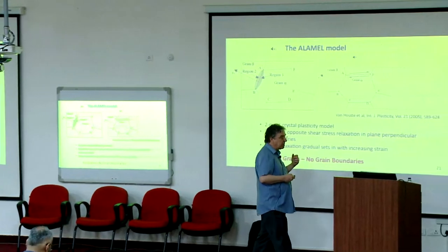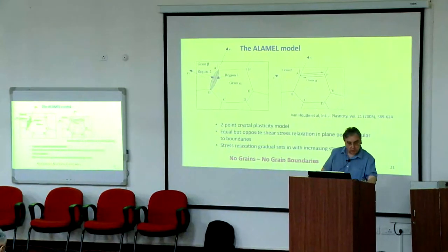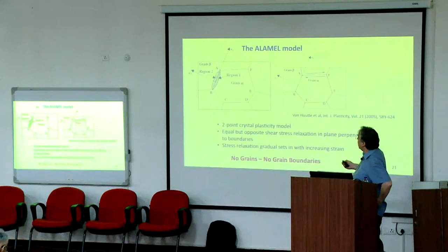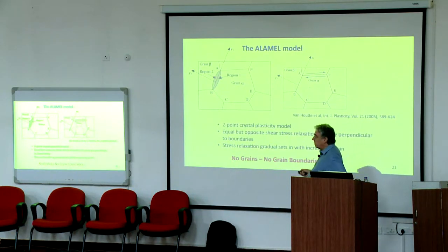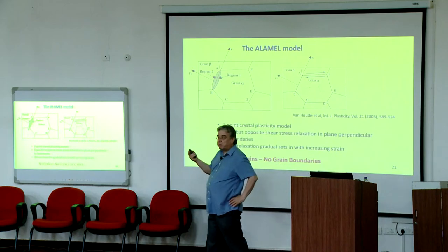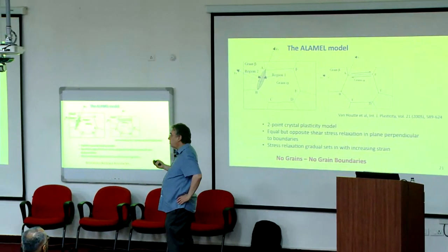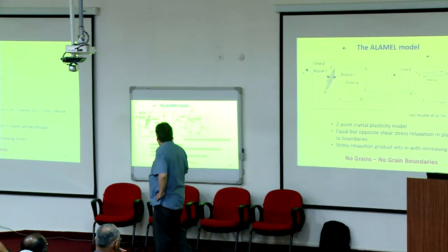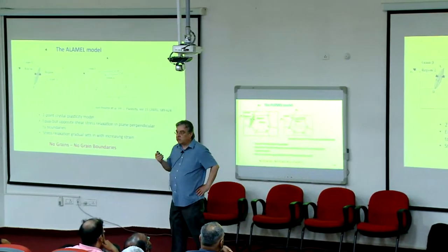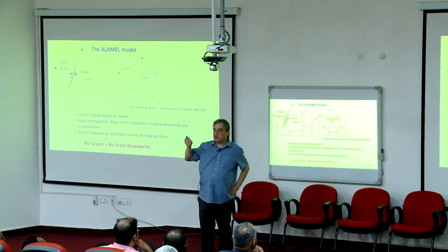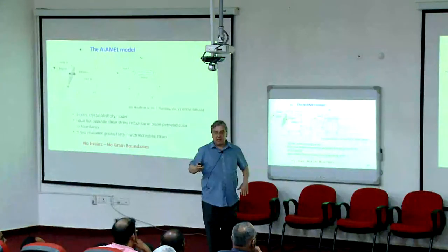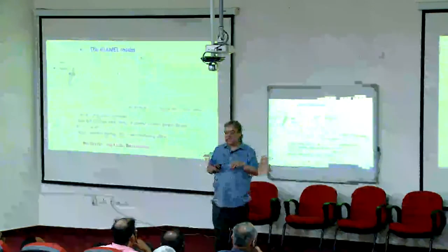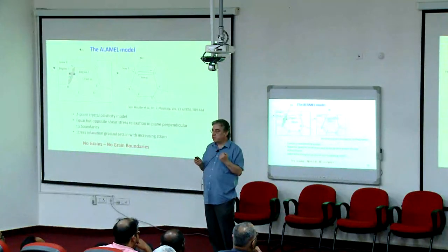I'm not going to go into much detail. One such model that we often use is the ALAMEL model. It stands for Advanced Lamel Model. The interesting aspect is that it's entirely different from a representative volume element model. We don't consider individual grains. We don't consider grain boundaries. We only consider crystal orientations. The crystal orientation in reality can be divided over many different grains in the material. So there is a conceptual difference.